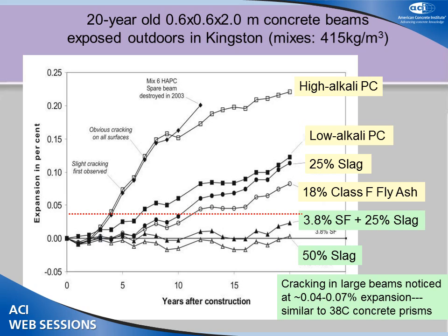And you can see that the high-alkali cements expanded the most, but then the low-alkali cements expanded and cracked as well. I'm showing the 0.04, but we saw the first observations of cracking. I didn't have it put on all the graphs here, but it's in the area between 0.04 and 0.07 is when we saw the cracking in the field, that we could see visual signs of cracking. But we only went out there once a year, so we didn't maybe catch the exact spot. So we know it was less than 0.07, but maybe it was down closer to 0.04.